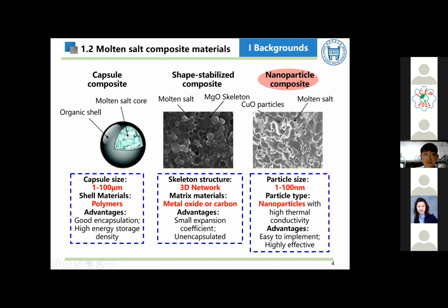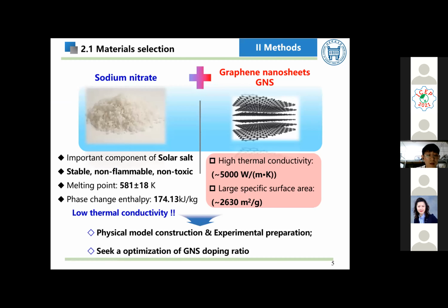In addition, the phase change enthalpy and specific heat also show contradictory decreasing or increasing trends. In this paper, we hope to explain the contradictory results through our work and seek the optimal doping ratio of nanosheet particles. Sodium nitrate, an important component of solar salt, was selected as the phase change material. Graphene nanosheets was selected as the nano-reinforcer.